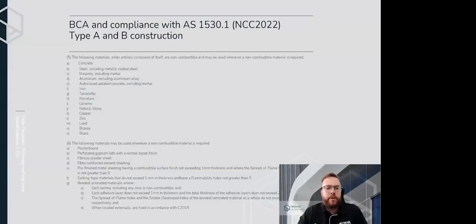And then down the bottom, it has the following materials that may be used wherever non-combustible material is required. It lists plasterboard, fiber cement sheeting, pre-finished metal sheeting having a combustible surface finish, sarking materials, and bonded laminate materials where the laminate, including the core, is non-combustible, the adhesive layer does not exceed 1 mm in thickness, and the total thickness of the adhesive layers does not exceed 2 mm.